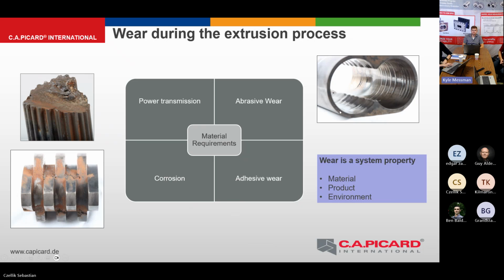Abrasive wear, like I said, we often see in the kneading zone, and here the shafts are really pushed apart, and you can see heavy wear in the zone. You see all the single kneading discs at the wall of the liner. And we have adhesive wear. We do not see that often, but it can happen that if one part is much softer than the other part, you have a material transfer from one to the other. That is then called adhesive wear.